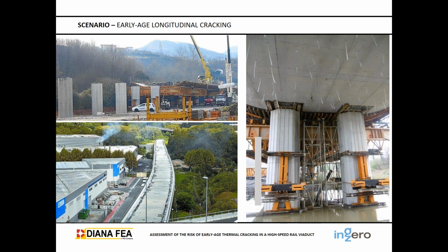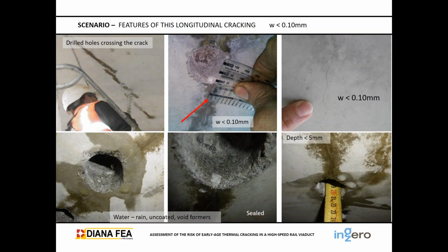Okay, we'll go on to the photographs, and now we can understand a little bit more of what we are seeing. The whole deck constructed, we see the cracks, the longitudinal cracks isolated, following a pattern, but not symmetrically. And we see the shorings, and the cranes are placing the void formers in this photograph. Okay, so we go on to the working site, and we made some drill holes across the cracks in order to see how they develop in the depth of the deck. We see that they are very small, less than 0.10 millimeters.